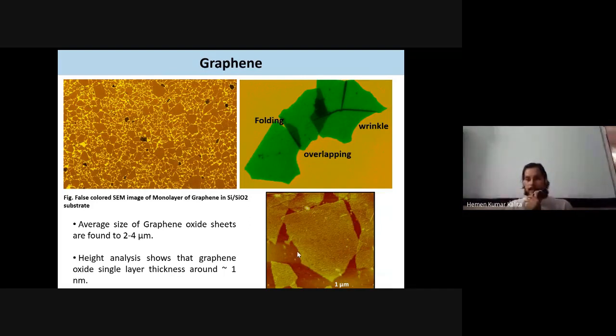AFM is not meant for the size of graphene. This is not a method to measure the size, though you can observe the size, but that is not accurate. For size measurement, we always use scanning electron microscopy. For height measurement only, we use atomic force microscopy. In atomic force microscopy, we get the height of the graphene, and if it comes around 1 nanometer, that means we can say it's a single layer of graphene.